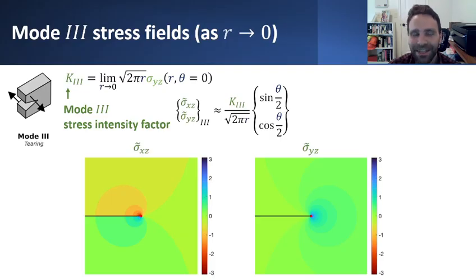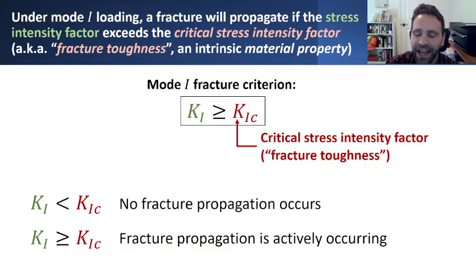Well, again, it means we can't really apply a purely stress-based failure criterion to evaluate when a crack will grow or when a crack will start. All that basically says we can't use a stress-based failure criterion. We need something else. And the something else that we're going to use is precisely this stress intensity factor. It's the thing that didn't zoom off to infinity in the limit as we got closer and closer to the crack tip. So even though the stresses zoom off to infinity, we know that this stress intensity factor, which is the stress multiplied by this extra square root of x or square root of r term, at least stays a finite value, even as you get closer and closer to the crack tip.